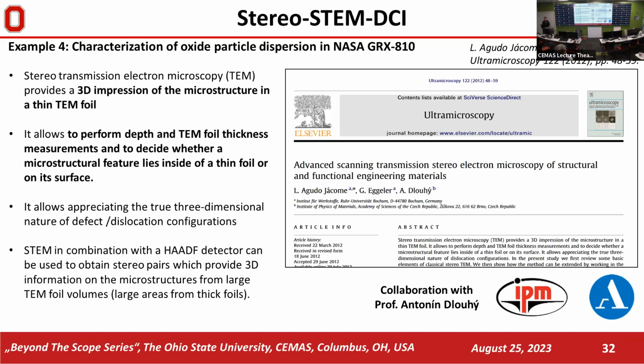So stereo TEM or Stereo STEM provides a 3D impression of the microstructure in a TEM foil, and it allows us to perform depth and thickness measurements to decide whether microstructural features lie inside the thin foil or on the surface. And I definitely have to recommend this paper if you're interested more in the theory and background of these classical methods used in combination with new instruments, and with using Stereo STEM to do characterization for this alloy. We have very good collaboration with Professor Antonin Dlouhý from IPM in Brno.